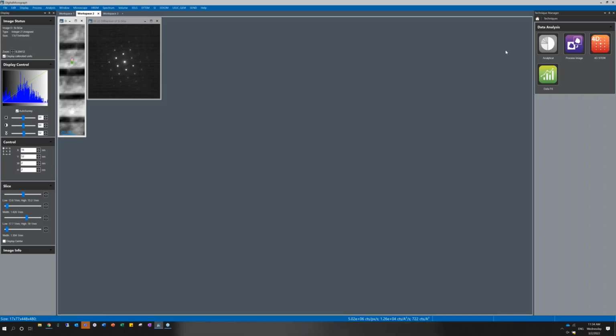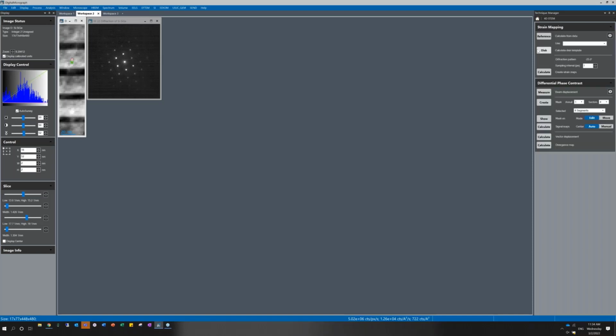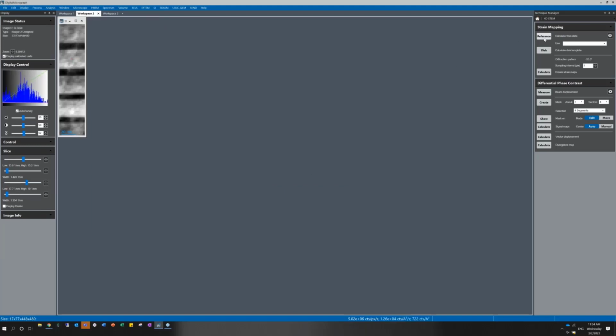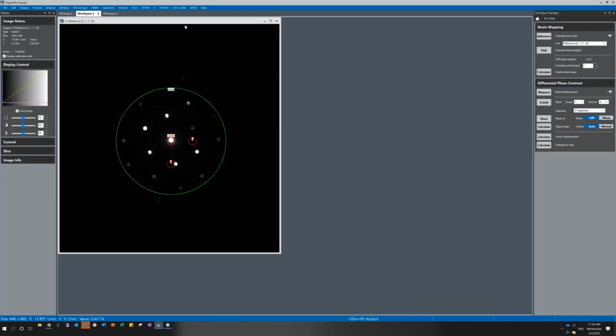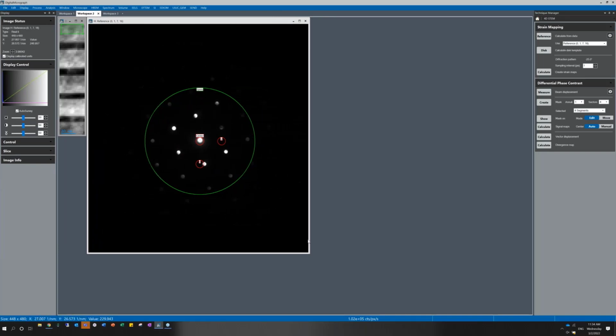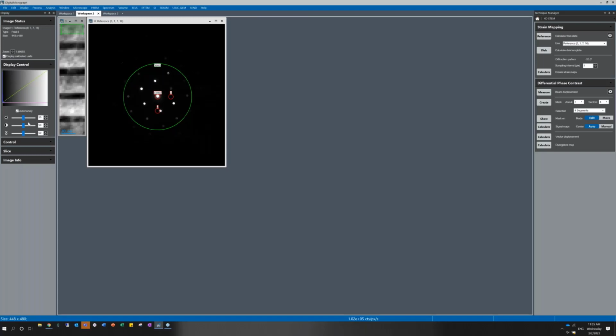Okay, so for strain mapping, what we do is we go here on the right-hand side to data analysis technique and select 4D STEM. And you can see we have strain mapping here. What you want to do is simply start from the top of the window and make your way down. The first step is to specify a region of the sample that is not strained to calculate the reference diffraction image. To do that, again, I right-click on my image and I select this unstrained area tool, and I draw this green box on my silicon layer, and then I go to my strain mapping technique palette and click on calculate reference from data. So the software automatically calculates a diffraction image that will be used as a reference to measure the strain.